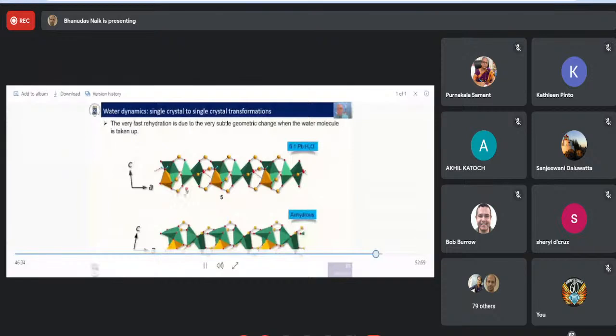And this one as well, if you look between the anhydrous and the 5:1 ratio here, you can see that there's a very small difference between the geometry. You see that there's almost no difference at all in the geometry. So it's a very small geometric change.